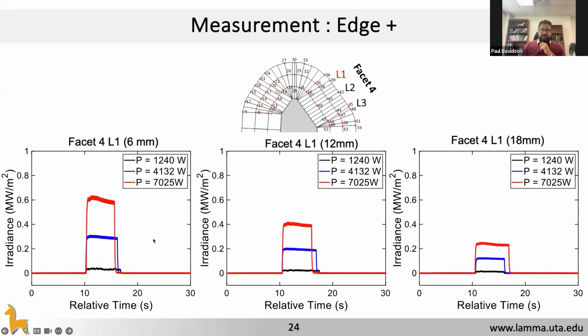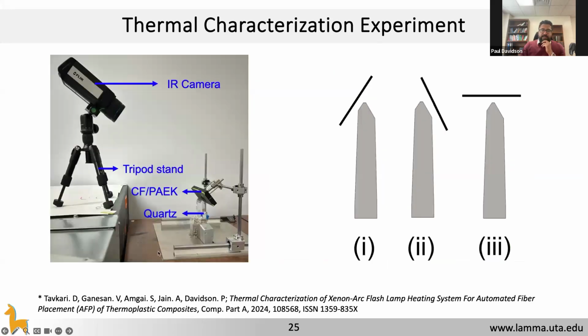Okay, so to understand that, we said, if we were to do measurements for everything using experiments, it is intractable. I mean, there would be so many experiments to do. So we said, let's first see how these flux profiles influence the temperature on the material by looking at a static test. That means we take the quartz block and put a plane of tape at different locations around the quartz block and measure the temperature.